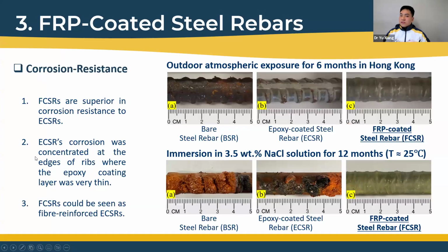To test the corrosion resistance of FRP coated steel rebars, we first placed different kinds of rebars in the outdoor environment in Hong Kong for 6 months. After the exposure, the bare steel rebar corroded, and the epoxy coated steel rebar corrosion mainly occurred at the edges of the ribs where the epoxy coating layer is very thin. The FRP coated steel rebar remained uncorroded, unaffected by the atmospheric corrosion.